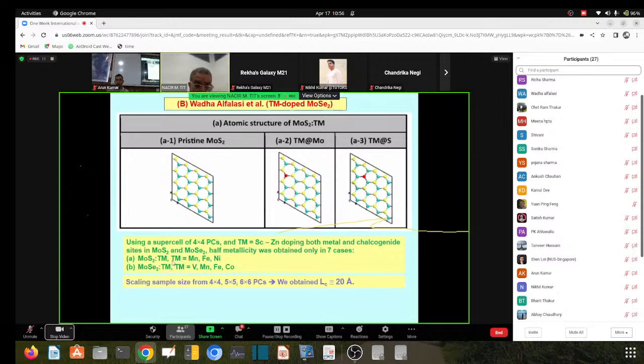MoS2 when it is doped with manganese, iron and nickel, and MoSe2 when it is doped with vanadium, manganese, iron and cobalt. So we did also some scaling to predict the ferromagnetic interaction, to what distance it can be carried out. We proved it to be also about 20 angstrom in the case of transition metal doping.